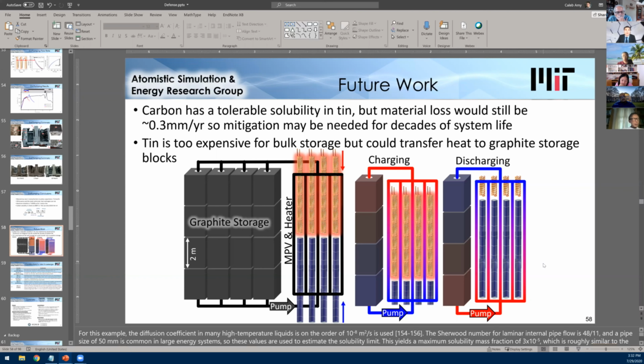The performance isn't quite as good because now your storage medium is not isothermal and it's a little harder to get heat in and out of it, but the storage medium is cheaper and the volume of tin you need is quite small. Tin is an order of magnitude more expensive, but you need at least 100 times less. So the cost of the tin is fine for heat transfer.